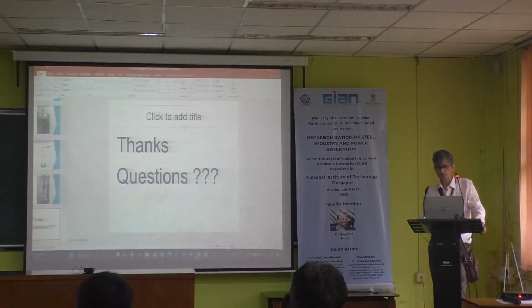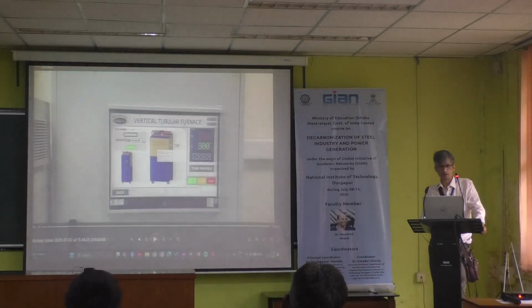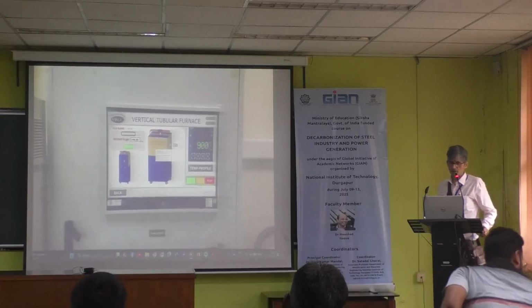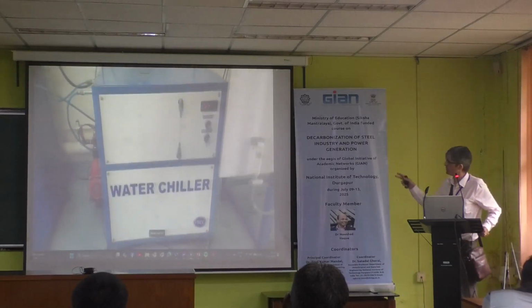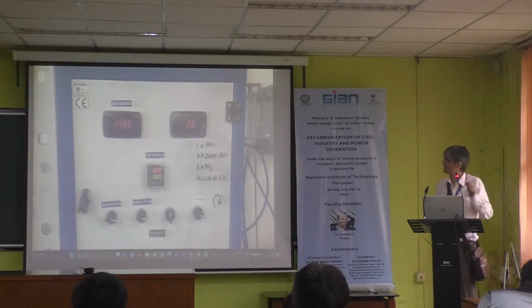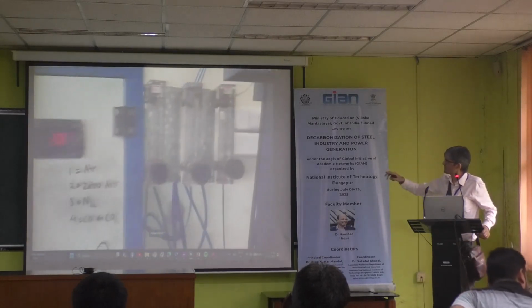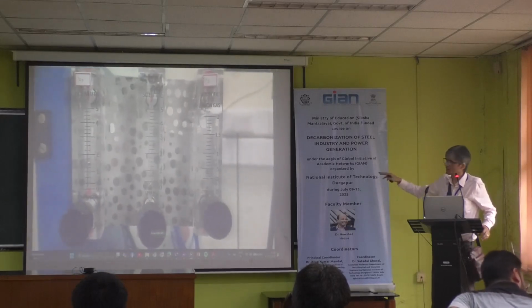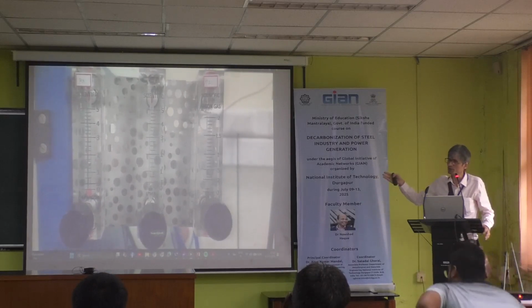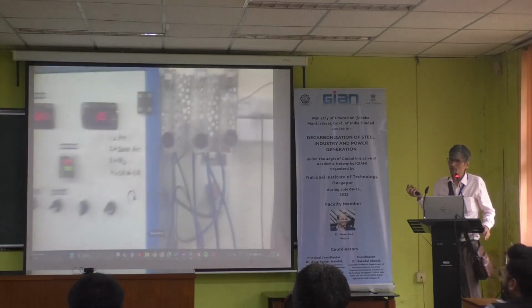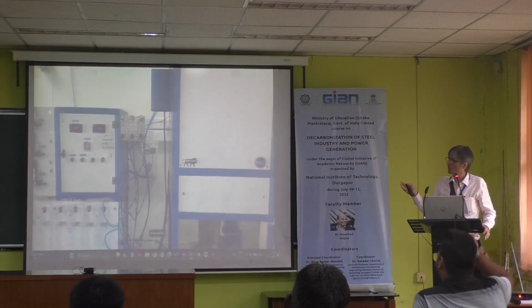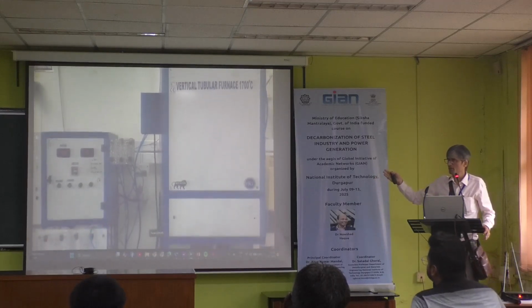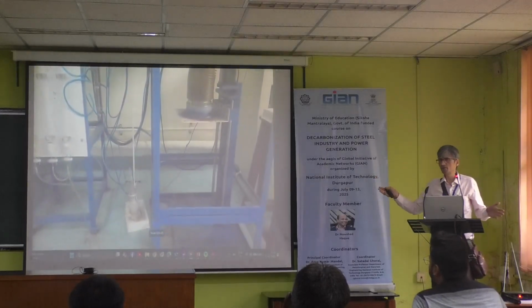But let me show you one video. This is the operation of a vertical tubular furnace while the hydrogen experiment was going on. This experiment is taking place at 900 degrees centigrade in the vertical tubular furnace using hydrogen. Right now we are using a combination of hydrogen and argon, with hydrogen at 10%, 20% and 30%, and the rest argon. The time duration and flow rate have been decided by stoichiometric calculations and by applying a utilization ratio.